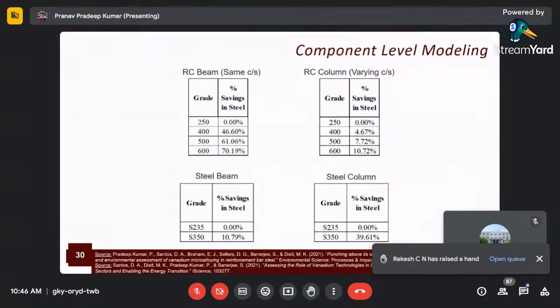So we see that there is a huge difference in the amount of savings with respect to reinforced concrete and steel sections. One of the reasons for reduced savings in terms of steel is because we have standardized steel sections. So we don't have a lot of choice. Even though we are enhancing the strength of the steel materials, we still have to abide by the standard specifications, and they have standard sections, and we don't have something in between two different sections. Due to that factor, we can see that there is reduced savings in terms of steel sections, but there's more savings in terms of reinforced concrete sections. And for the analysis purpose here, we used Eurocode specifications.